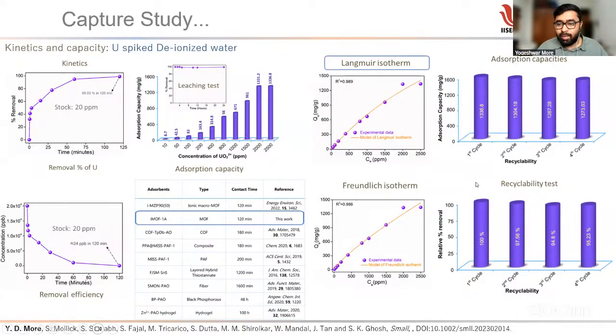Then we went for the adsorption capacity for different cycles. Since we know what is happening on the first cycle, we adsorbed the uranium, then removed the uranium using alkaline KOH, like it is an ion exchanger. And then we again tried the adsorbent and placed it in the water. So first cycle, second cycle, third cycle, fourth cycle.